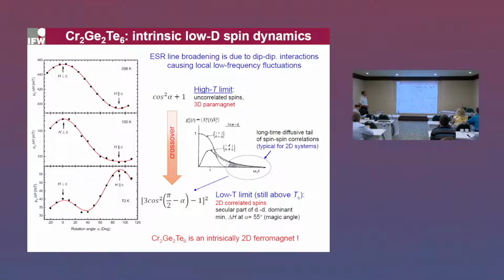Its time dependence matters. Usually in the paramagnetic limit of a three-dimensional system, the spin correlation function decays very rapidly on the time scale of the isotropic exchange interaction. But in two dimensions, there is a long so-called diffusive tail of the spin-spin correlation, where the long wave correlations survive at times much longer than this characteristic scale of the isotropic exchange interaction. And in the limit of the short time scale, all kinds of dipole-dipole interactions, the so-called secular and non-secular terms, contribute to the line width, and they give rise to a very specific cosine squared plus 1 angular dependence, which we indeed observe at room temperature.